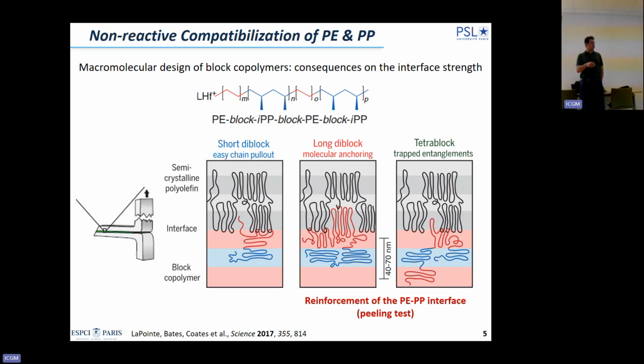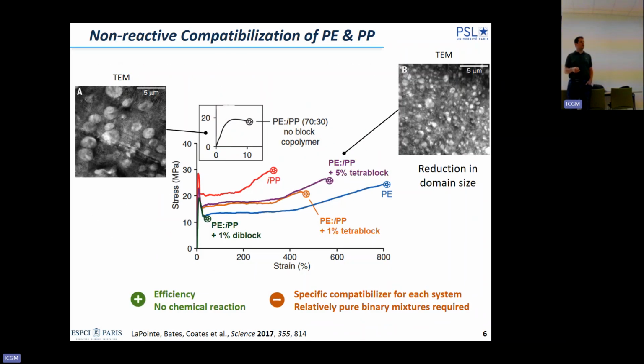So they showed this with peeling tests. Here you have PE, here you have PP, and they put their copolymer at the interface and measured the adhesion mechanical property. It's a very nice paper, so I really invite you to read it if you did not do it. They went from short diblock to long diblock and to tetrablock, long or short. And what they propose is what I mentioned briefly: it is very important to not only have entanglement in the amorphous phase, but to have co-crystallization. So this is, I think, one of the take-home messages.